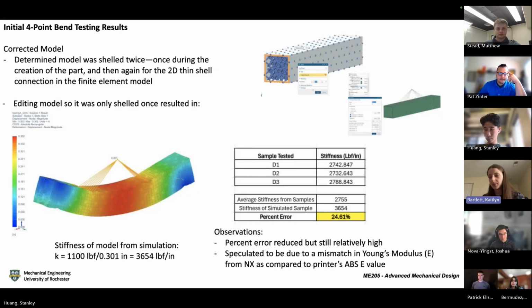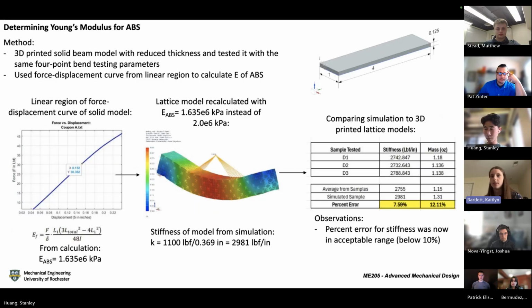But the percent error was still pretty high between the two, so we had to hone in on what was really contributing to the discrepancy. We determined that the Young's modulus for ABS was different in NX than what we were using for our ABS coupons. The way we determined the Young's modulus was that we 3D printed another coupon to test with. This one is in the top right corner. It's just a thin rectangular beam made of ABS as well.